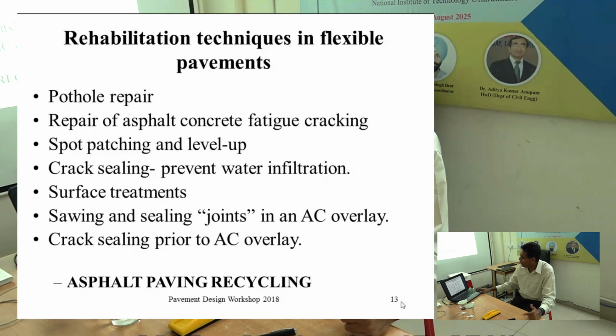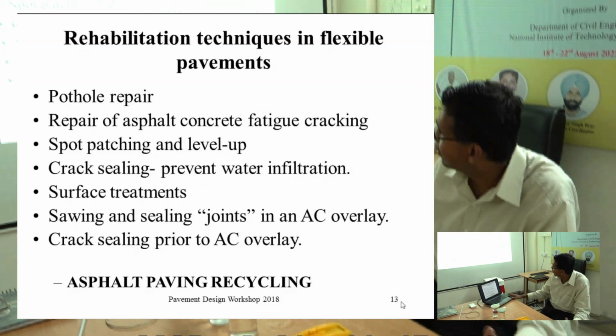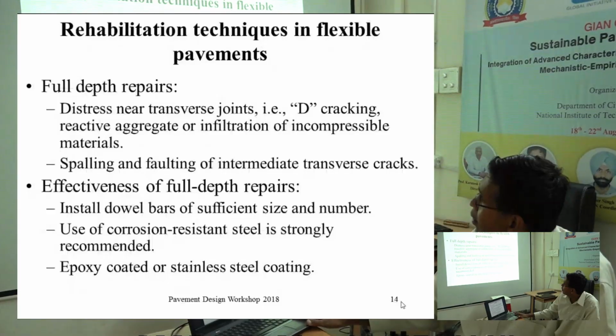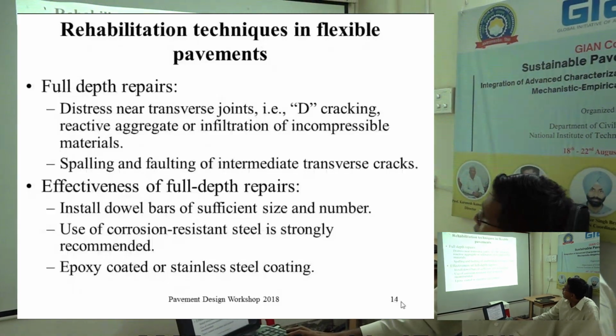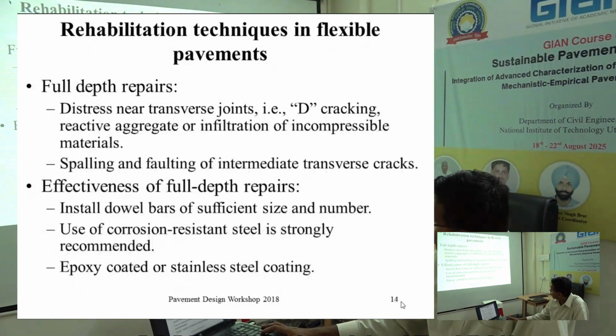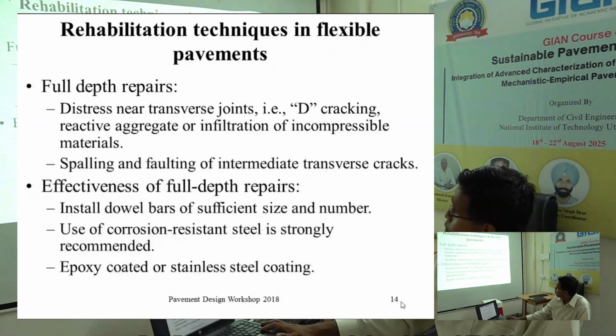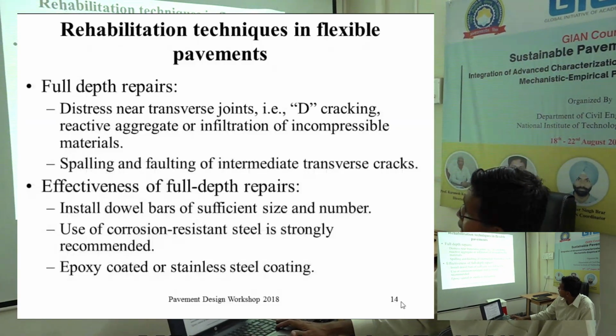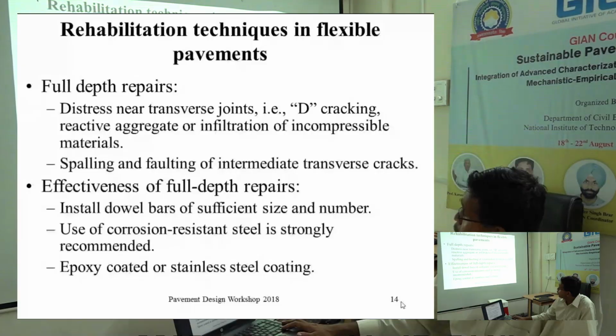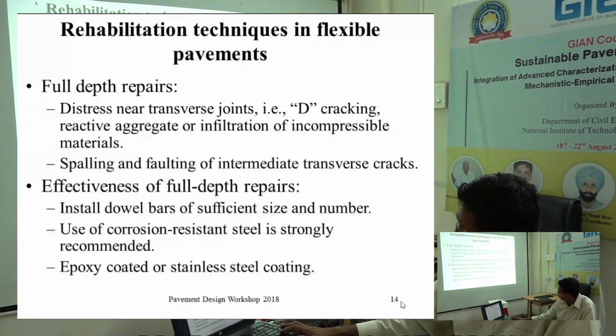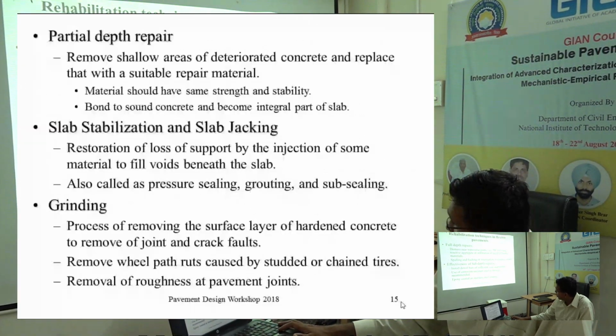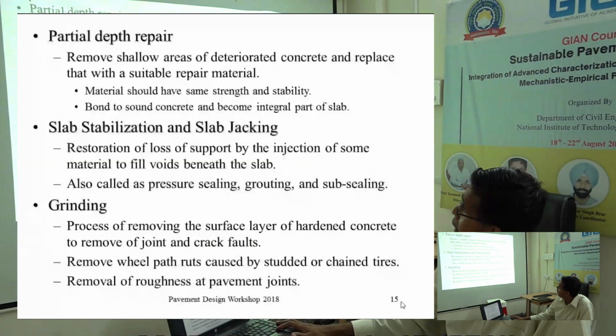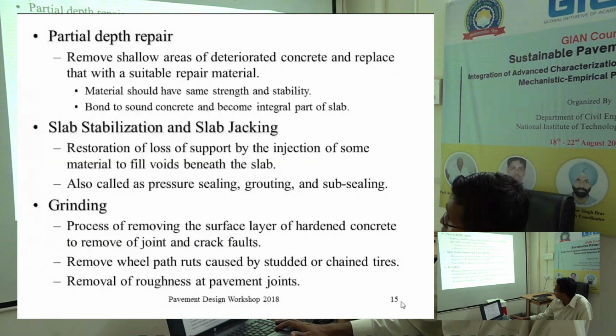Pothole repair of asphalt, concrete, fatigue cracking, crack sealing, surface treatment. Full depth repairs. Distress near transverse joint, cracking, we looked at that. Spalling and faulting of intermediate transverse cracks. These are the techniques. You have to install dowel bars, corrosion resistant, epoxy coated, stainless steel coating. Partial depth repair, you must remove shallow areas of deteriorated concrete. They should have the same strength and stability. You have to do slab stabilization.